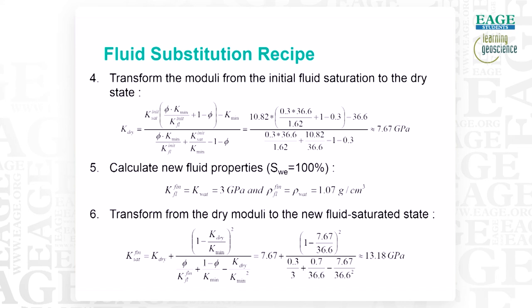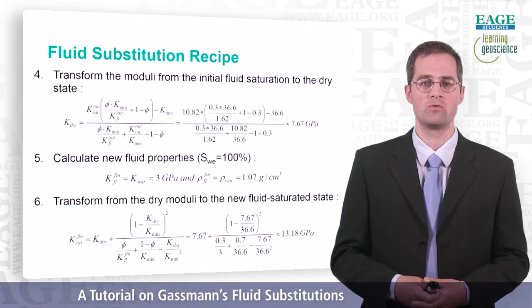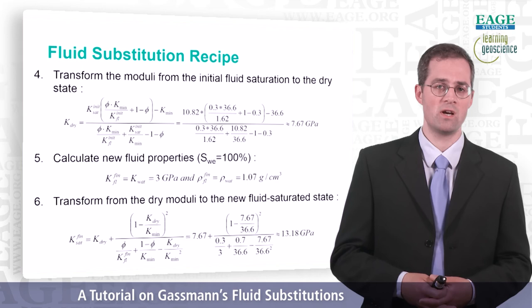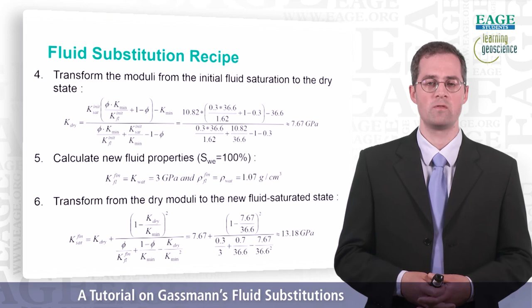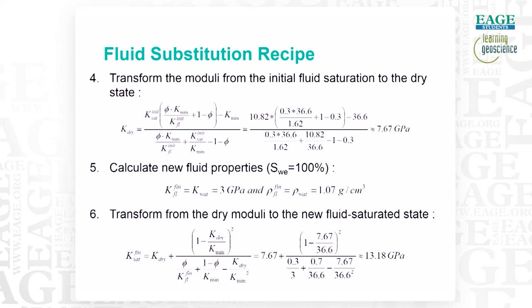Then we need to think of the new fluid properties. In our case, we want to put only water in the porosity, which is quite easy. We already know the properties of water, namely 3 gigapascal for the bulk modulus and 1.07 grams per cubic centimeter for the density. And then we will apply Gassmann the other way around, starting now from the dry bulk modulus that we have computed previously and using the new fluid saturated state. You just have to use the equation which is written here in bullet point number 6, and in the end we get 13.18 gigapascal.